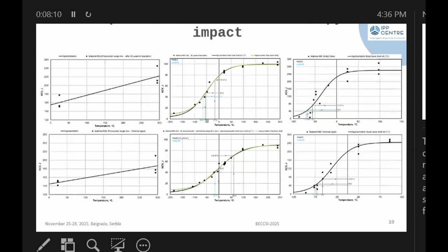This slide shows the result of determining impact toughness. As you can see, thermal aging leads to a reduction of upper shelf energy and an increase of DBTT for ferritic steel, and a slight reduction of upper shelf energy for austenitic stainless steel.